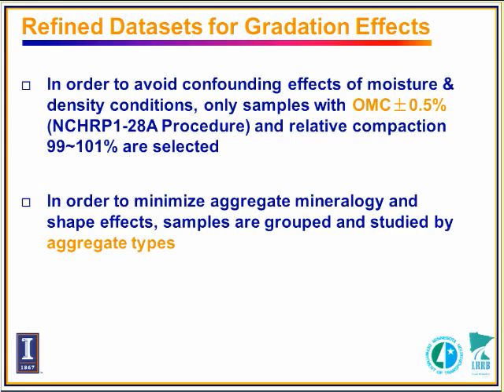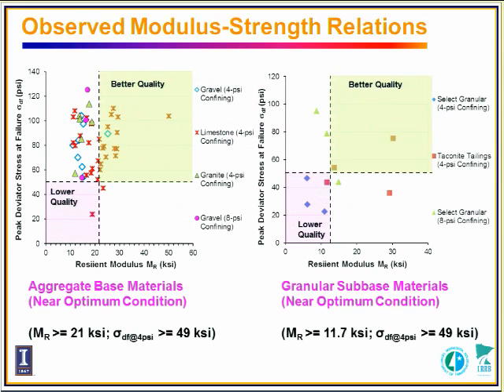As well, in order to minimize aggregate mineralogy and shape effects, we grouped each sample according to their aggregate types. And this is just the typical results showing the modulus-shear strength relationship. According to the mechanistic classification, resilient modulus and shear strength are indicators for the mechanical performance. So this figure shows, for example, 4 types: gravel, limestone, granite, gravel, at different confining pressures.